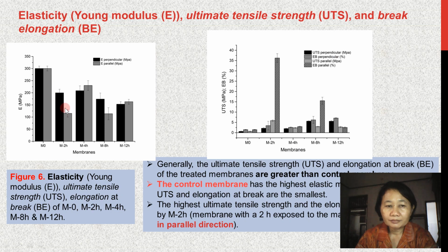But the value changes randomly. And also for the ultimate tensile strength and elongation at break, generally the ultimate tensile strength and elongation at break for the treated membranes are bigger compared to the control one. For the elongation at break, especially for the chitosan membranes exposed to a parallel magnetic field for 2 hours, it has a very big number, more than 35%. It means this membrane is very elastic.